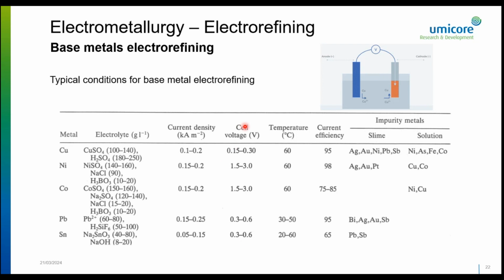And the reason for this is that the theoretical cell voltage, if you look at the reduction potentials, is 0, because the oxidation and reduction reaction are the same. So it's actually a very energy efficient process. The downside of the process is that it's slow, but it's a very efficient process. And there's a lot of metals you can process in this way, like besides copper, also nickel, cobalt, lead, tin, but it's mainly applied for copper.